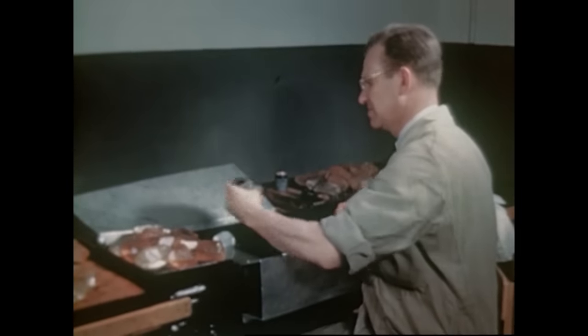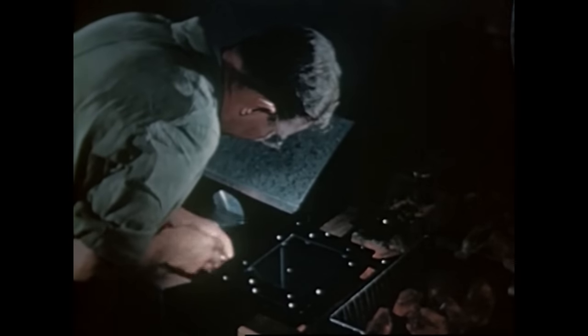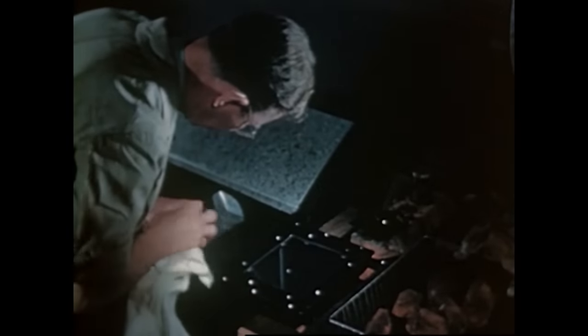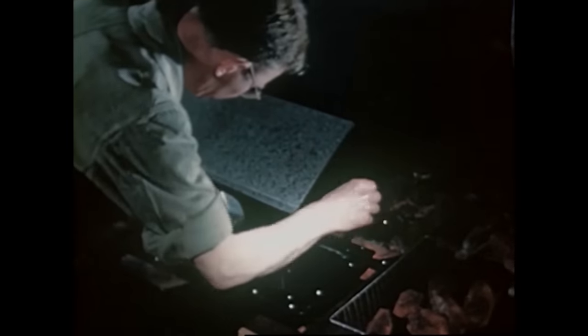The inspector submerges each quartz crystal and rotates it in a strong beam of light. Under oil, the surfaces of the quartz vanish, letting the interior imperfections come to light for the inspector to observe. From the character of these imperfections, he judges the usefulness of each piece. After the quartz has been examined under oil in polarized light, it is marked according to its quality.